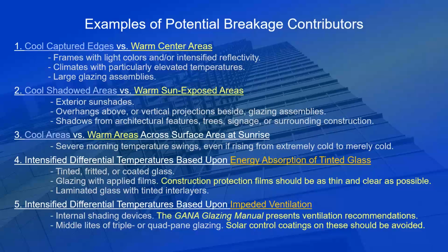Severe morning temperature swings, even if rising from extremely cold or merely cold, where you have a buildup of solar heat gain from the direct energy from the sun, can lead to condition number 3. Tinted, fritted, or coated glass, whether it's a ceramic frit on the inboard surface or a silicone emulsion, a paint on the inboard surface, applied films, and this is one of the reasons why third-party field-applied post-construction films can result in the loss of an IGU warranty if they're applied to either the outboard or the inboard surface of an IGU. And then laminated glass, those can all result in situation number 4.